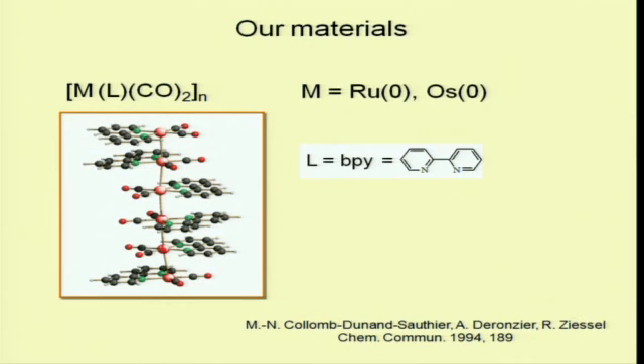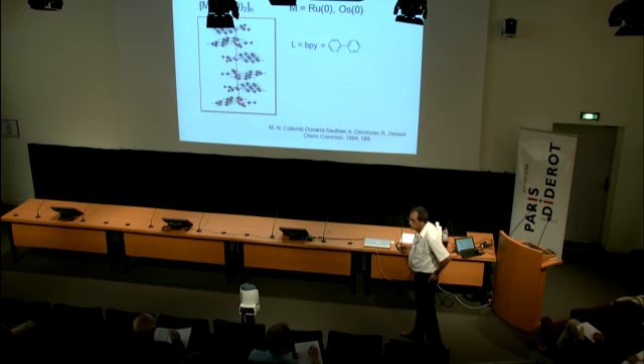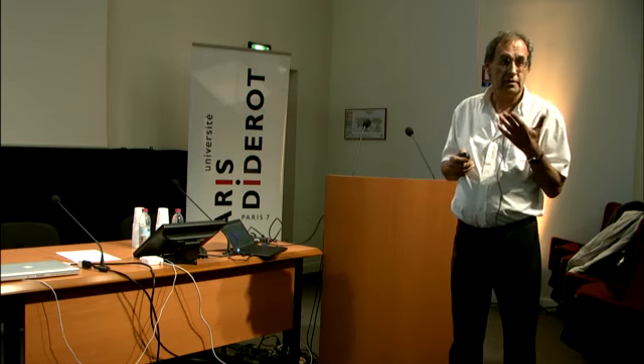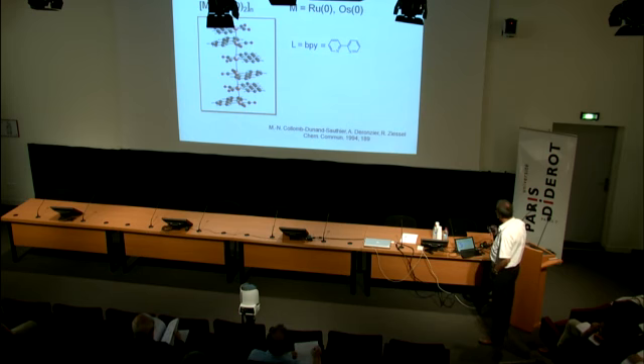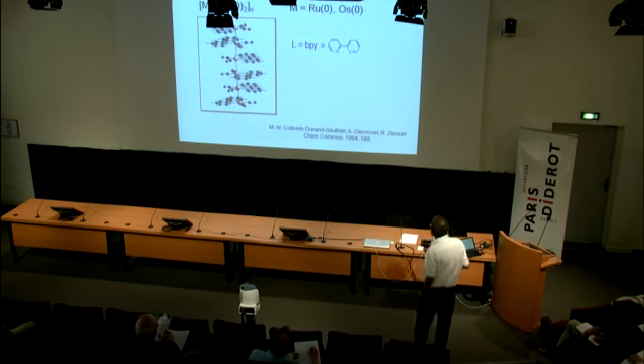At the beginning of the 90s, we discovered a new class of compound by pure chance. It's a very unlikely material. As Raymond said at this time, impossible. He said that. So our material is a sort of polymer based on a metal-metal bond. For instance, M here is ruthenium or osmium, and each metal is surrounded by one or two carbonyl groups and a diimine ligand like a bipyridine. And there is a flat zigzag chain to arrange all the system.